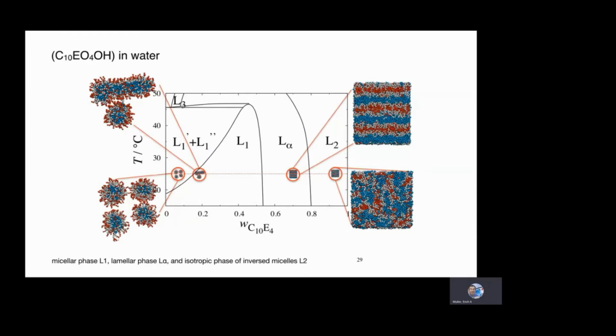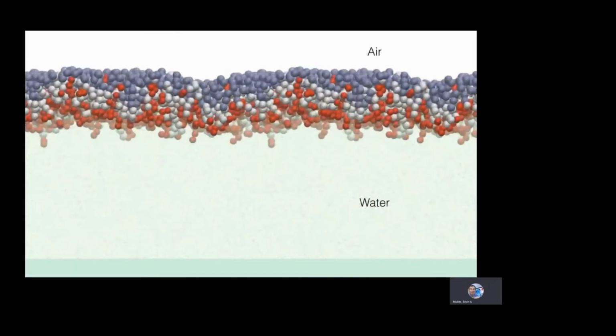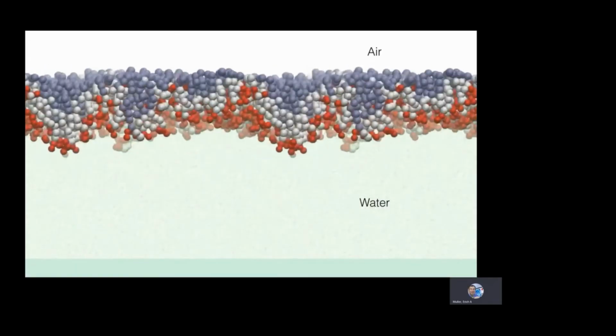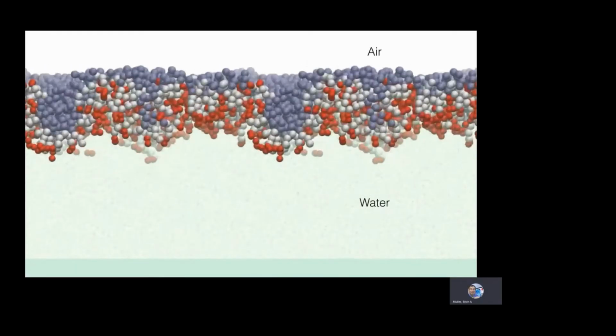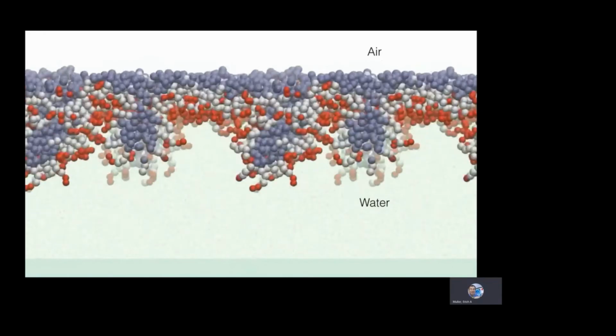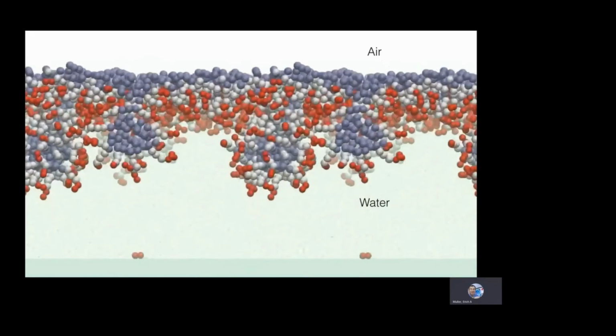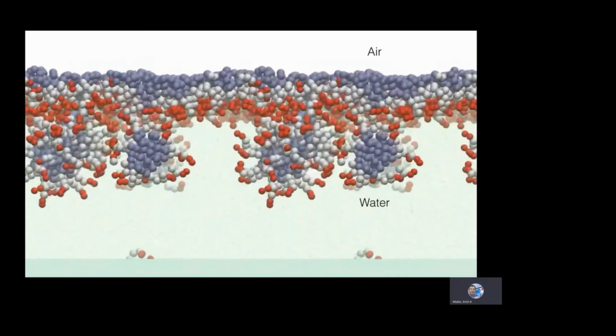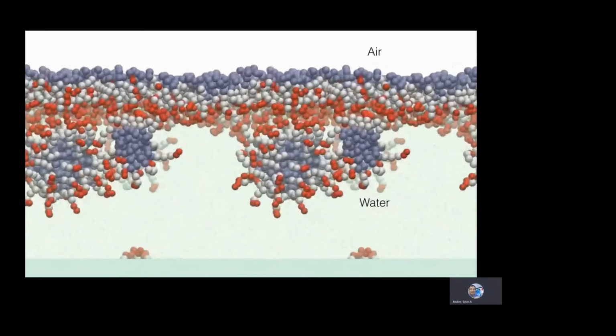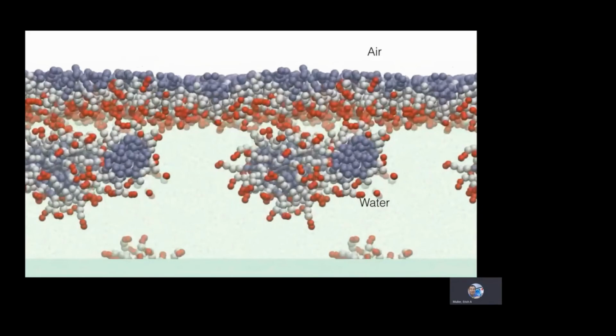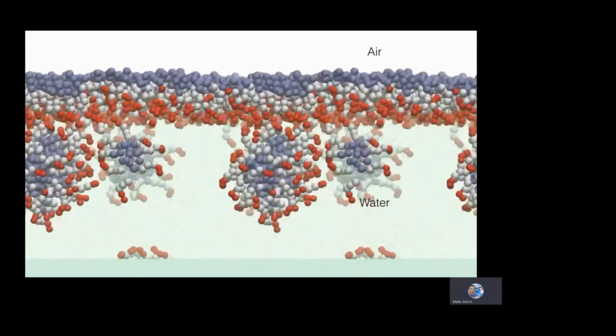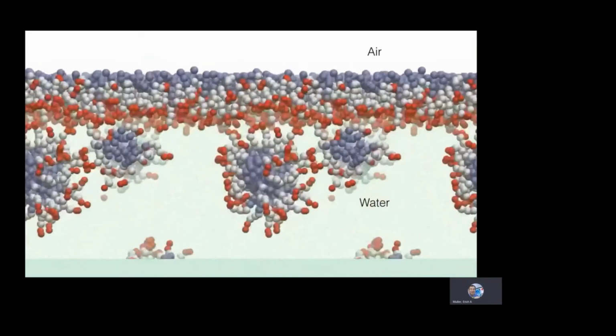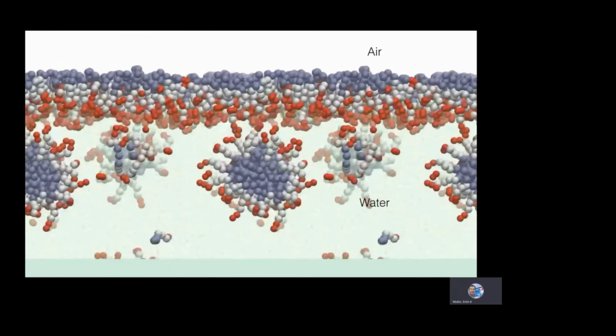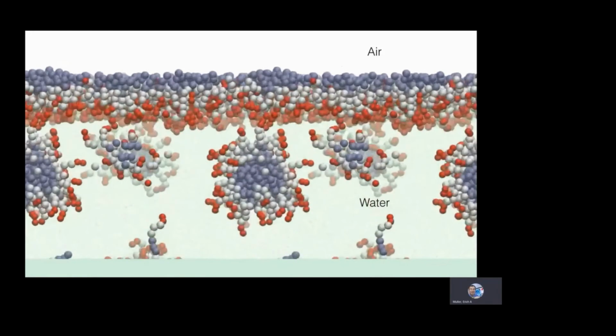In the following slide, I'll show you a movie of what happened in our model when we put it into the water-air interface and put an excess number of surfactants at the interface. What happens, of course, is that we exceed the CMC, or critical micelle concentration, and the micelles will start detaching from the surface in order to maintain a maximum amount at the interface.